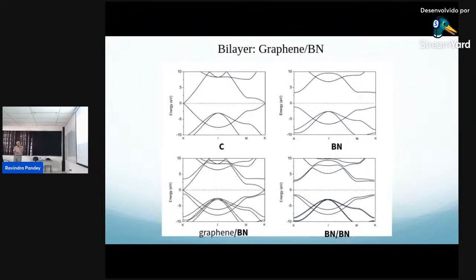So let's come back. So what we did again is this calculation, graphene boron nitride monolayer, you optimize the distance, look at the total energy, and when you have the minimum energy, you say, I have the equilibrium configuration of the system. And once you have it, you do a lot of other post-processing tools to look at the band structure. So this is the energy, and this is the high symmetry points. So pick up the graphene, graphene. We have boron nitride monolayer. This is a boron nitride bilayer. This is our heterostructure graphene boron nitride.